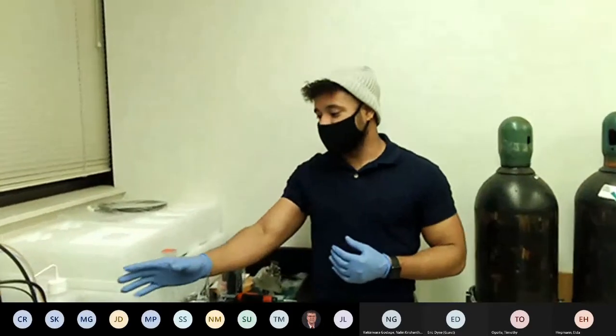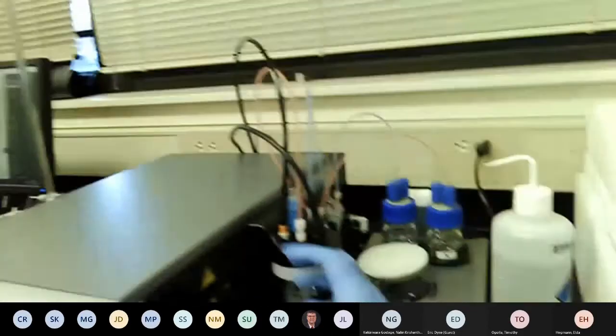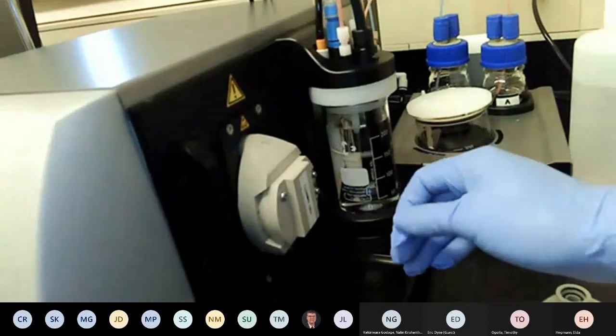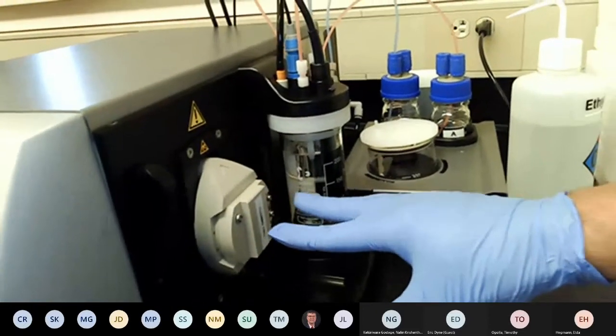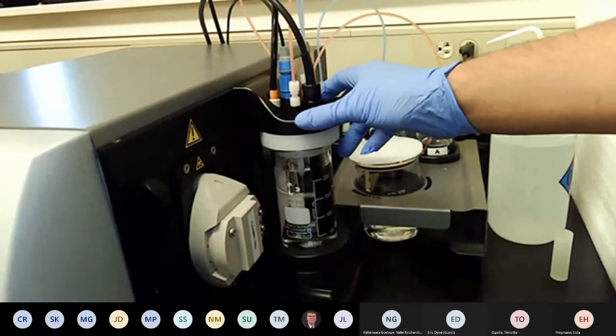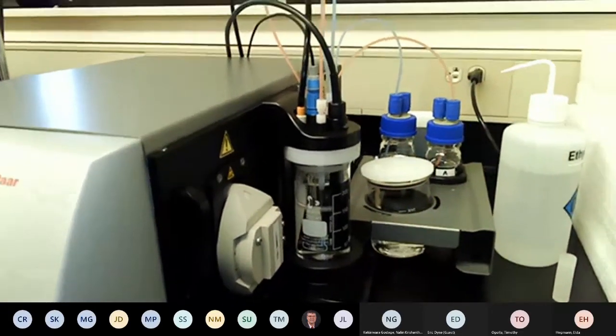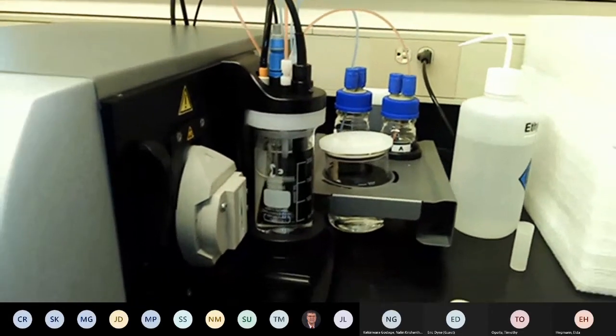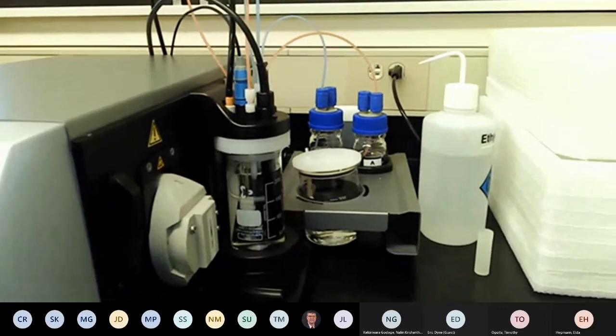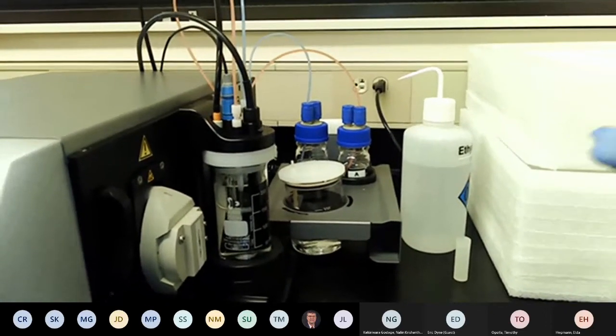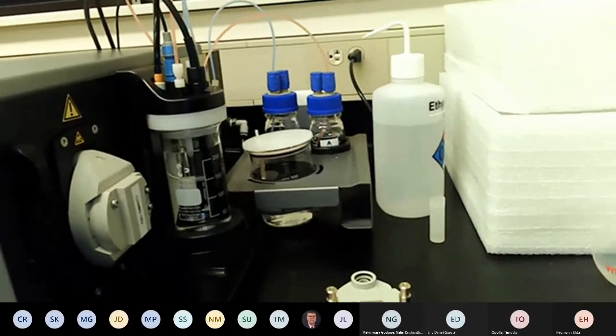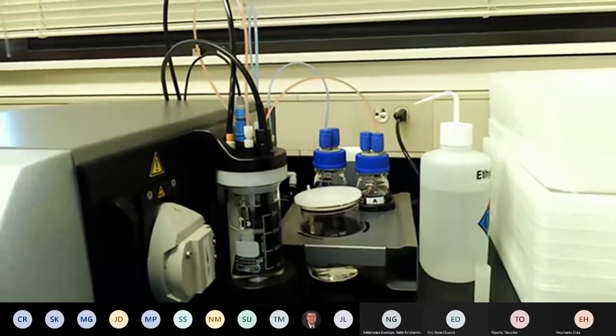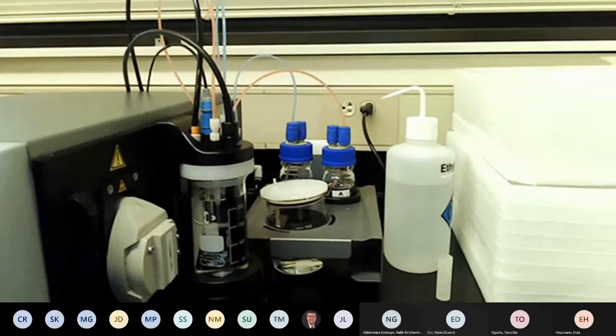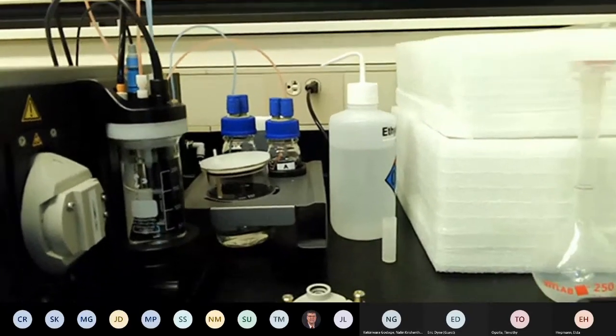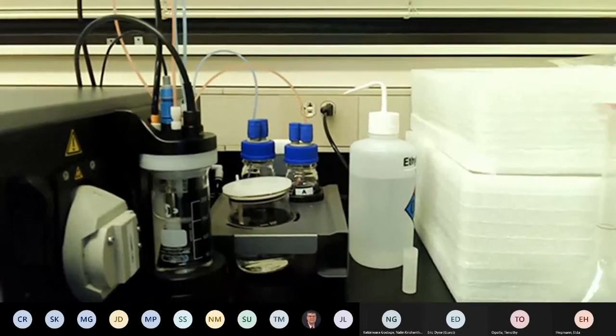On the side of the instrument, you have a few other components as well. The main one that you see here, of course, is the measuring cell, and we'll talk about these in a little bit more detail shortly. This is the area where you have your electrolyte solution. Most commonly, you'll be using about 0.1 or 0.01 molar KCl solution, in water, of course. It's very, very important when you're creating these solutions to use ultra high pure water. ASTM 1 would be the equivalent of the quality of water needed.